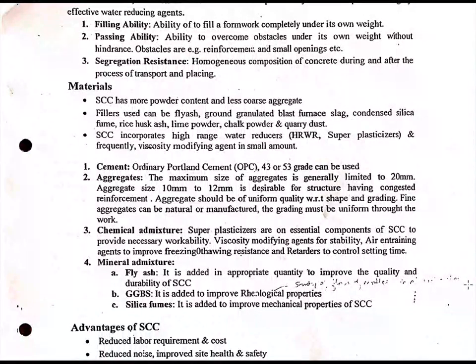Those aggregates should be of uniform quality and should also satisfy all the testing requirements of the aggregates. Similarly, when we take up the chemical admixtures, as the concrete has to flow, it has to have some plasticity, that is, flowing ability. To do that, we cannot add more water to achieve the flowability. To achieve more workability, we cannot add extra water. To achieve that workability, we have to use super plasticizers.